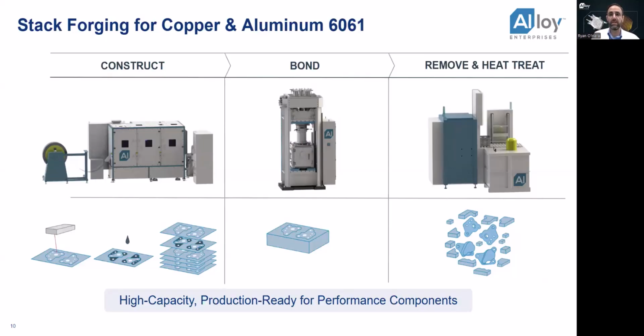And because there's no melting, we can achieve the very fine internal features without worrying about molten metal clogging them, which is a limitation of other processes. The result is a solid block of aluminum or copper with the parts embedded inside. From there, we unpack the block using strategic weak points and the inhibition layers to separate the finished parts.